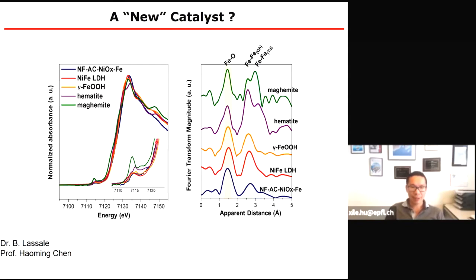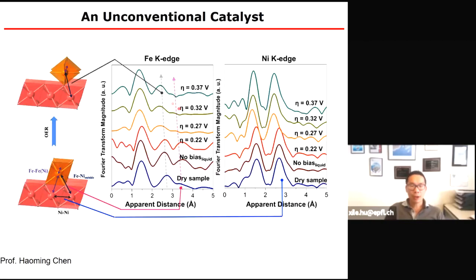We use various techniques, including especially X-ray absorption spectroscopy. We can look at the edge energies. We can look at the EXAFS to look at the fine structures, and we quickly realize, with our collaborators here, that for the iron part, the iron oxyhydroxide cluster, it contains only octahedral-based structures. And so that is useful. So it will be similar to gamma iron OOH. We can also look at the data under operational condition, in operando, and look at both iron and nickel edges.